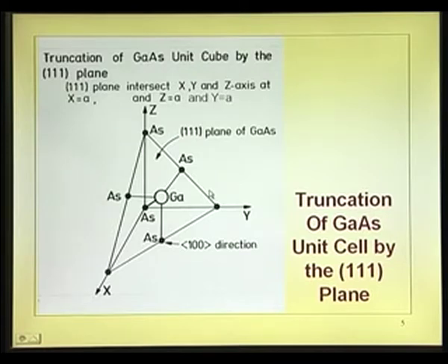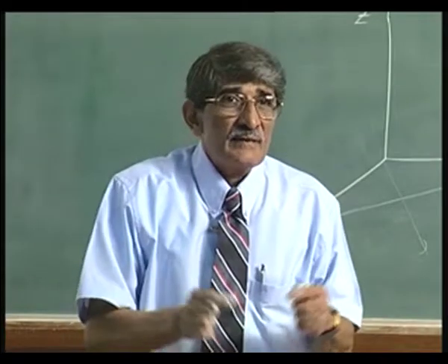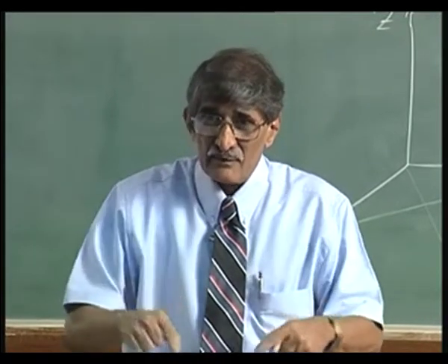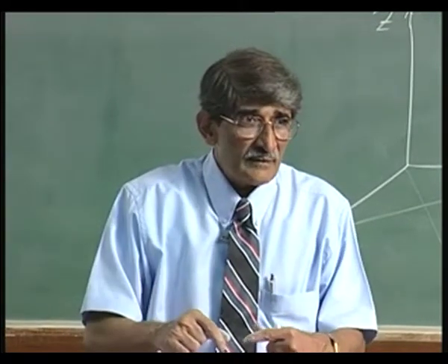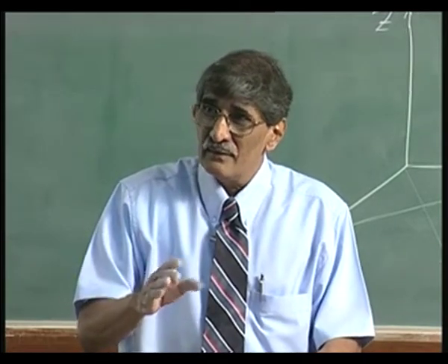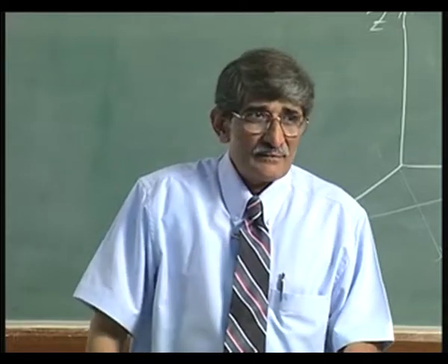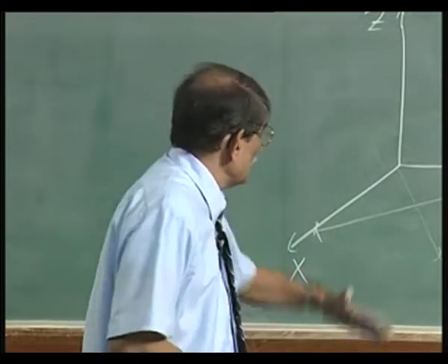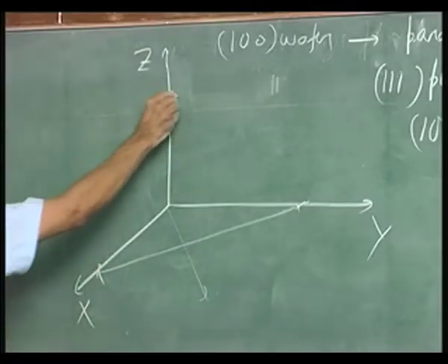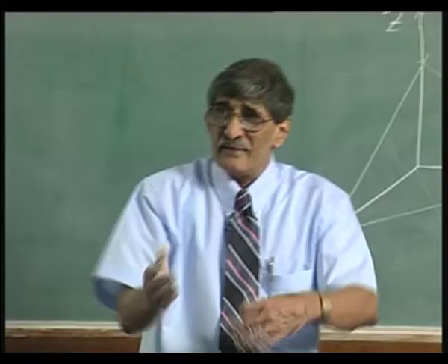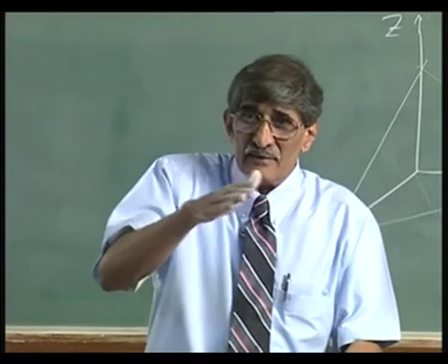So, if you see the wafers, when you dice them into individual chips, you scribe them and make small chips which are 1 millimeter by 1 millimeter, you see the edge of those in silicon will be at an angle. It can be like this or like that, because after all there is a plane like this or also going down. So, depending upon which way the force has come, you will see it going like this or like that.